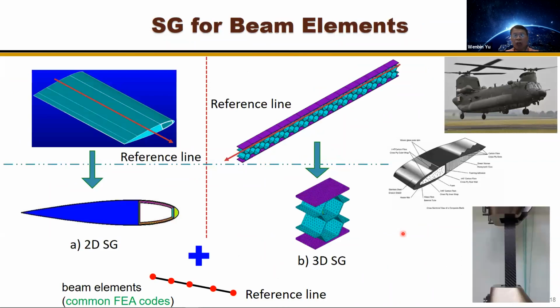How about if we have a very long structure? For example, helicopter rotor blades. If we have a uniform cross-section, or the blade can be considered as formed by piecewise uniform cross-sections, then the structure genome will be the cross-section. And if we also have heterogeneity along the spanwise direction, we're dealing with a three-dimensional block. What we want is torsional stiffness and bending stiffness for my beam models. That will be done at the one-dimensional level. And after we've done the beam analysis, we can do dehomogenization to get the stress distribution over the cross-section over